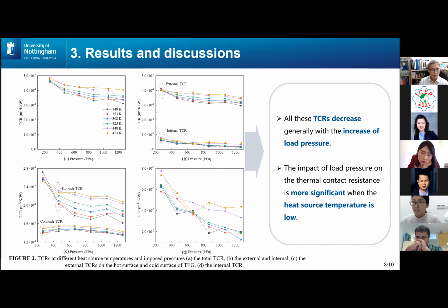Okay. The pressure we tested in our experiment, the largest is 1,200 kilopascal. But if you further increase the pressure, the thermal contact resistance will decrease further, but the degree of the decrease may not be that large.